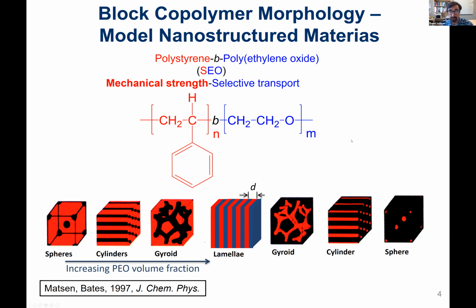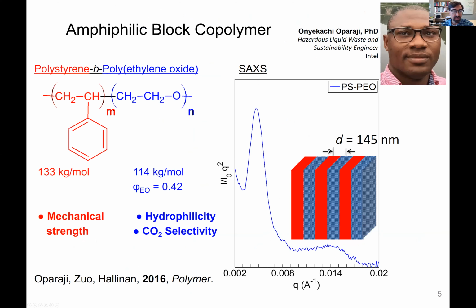Depending on the relative ratio, the value of N and M of your polymers, you can get all these well-defined morphologies, or structures, with a characteristic size D on the order of 100 nanometers. So I'm going to focus first on the lamellar phase, and we actually synthesized one of these polymers in my lab, relatively high molecular weight, so that it can make a dense freestanding membrane.